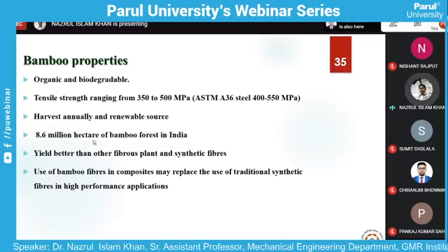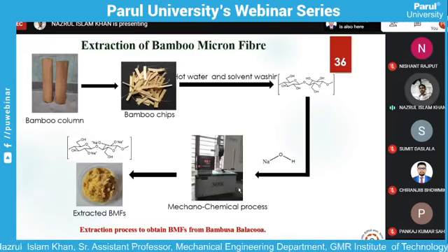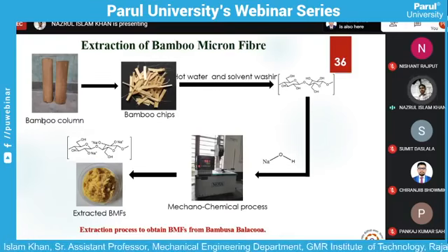There is 8.6 million hectares of bamboo forest in India, so there's better yield, and you can easily extract the bamboo fiber. This is the process through which we prepared the fibers from bamboo: first we took the bamboo, then prepared chips of bamboo, then extracted the cellulose.